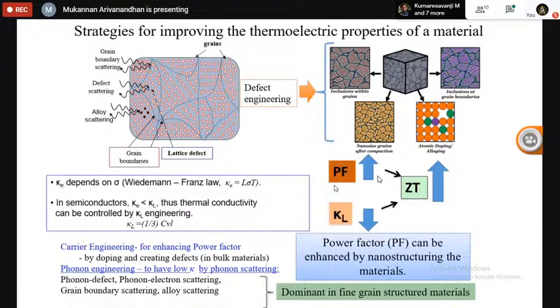So how can one increase the efficiency? Obviously, to increase the efficiency, you have to increase the figure of merit, as we have seen from the previous slide, right? So if you want to increase the figure of merit, here is the strategy. This is a schematic of a nanostructured bulk material. If you have this kind of nanostructured bulk material with all these grain structures and some kind of defects, grain boundaries, alloying and lattice misfit, then this kind of nanostructured bulk material with a reasonable amount of defects is quite beneficial for improving the thermoelectric performance. So how the defects are beneficial, let us see here.